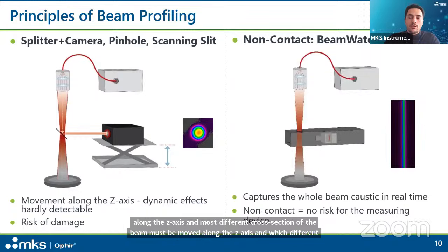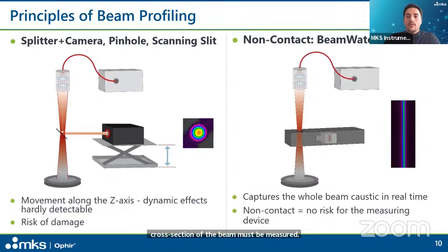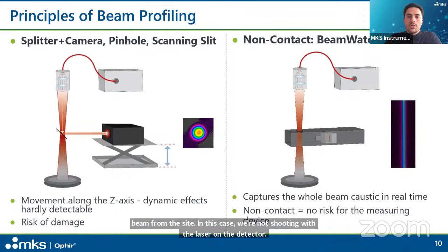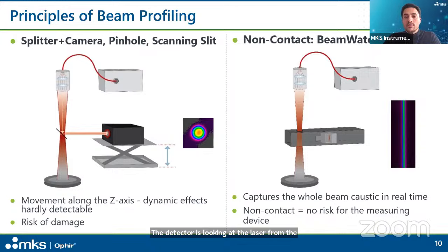The second option is a camera that captures the Rayleigh scattering of the laser beam from the side. So in this case, we're not shooting with the laser on the detector. The detector is looking at the laser from the side, and we call it beam watch. It is a non-contact measurement, so therefore there is no upper power limit. You cannot damage anything. And the whole beam caustic is captured at once and can be followed live. So all parameters can be measured immediately in real time. And you can, in this case, see and track the focus shift.